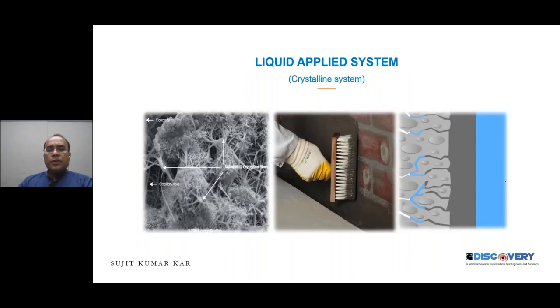This is an example of a crystalline based system, which we are recommending. This is the microscopic view of a crystalline system, where it is designed so that when the crystals come into contact with free lime and water, they form these kinds of crystals, and they penetrate into the porosity of the concrete. You can see these are the pores, and when these crystals come into contact with water, they form crystals and make the entire structure completely sealed.